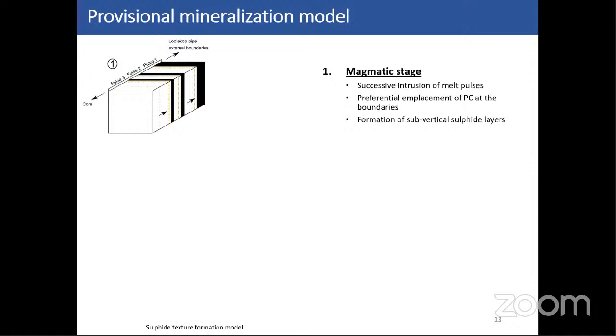Yes, and the different textures we see, and the difference between the sulfide layers observed with a microCT and the small grains disseminated within the gangue, as shown with mineral mapping with the MLA, is related to the variable magma flows during the emplacement of the phoscorite carbonatite intrusion. As a matter of fact, high magma flow rates prevent the coalescence of sulfide grains, which triggers a dissemination within phosphorite and banded carbonatite, whilst low magma flow rates allow the binding of these different sulfide blebs in the magma and the formation of the different assemblages we've observed with a microCT analysis.